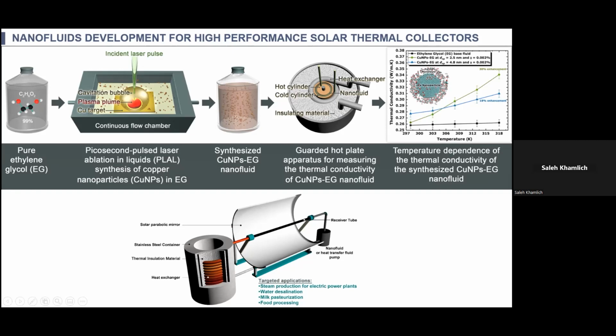So sometimes you think that you are not doing something very good, but at the end of the day, it gives better results. And this is what we found, 30% enhancement. So what is the beauty of this? That our nanofluid, we made at a very low volume fraction of 0.002% for the first time. Because in the literature, there is no report showing a nanofluid with this concentration having this enhancement. So now we are saving materials by using only a small amount of nanoparticles and having higher enhancement.